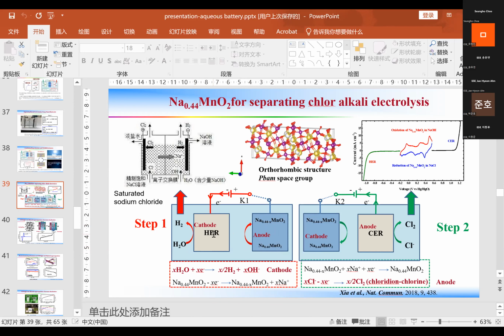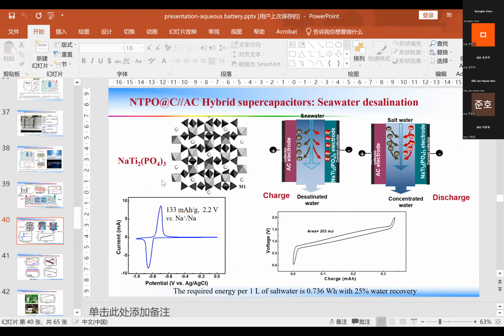and water is oxidized to oxygen or reduced to hydrogen. Then in the discharge process, the materials go back to their original state, and the chloride ion is oxidized to chlorine. So we can separate chlor-alkali electrolysis. We can also use sodium titanium phosphate, a good material for sodium intercalation and de-intercalation, for seawater desalination.